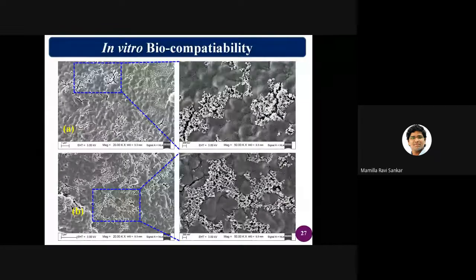And once you do this, then you have to go for in vitro tests. The first test that you can do is the biocompatibility test. The biocompatibility test will give you results under SBF studies, simulated body fluid. You can cross-check here: it looks like a coating, like a black color, which is not black. It is also white compared to this apatite layer formation, which is an amalgam of interaction of minerals and protein exchange with respect to the coated surface.